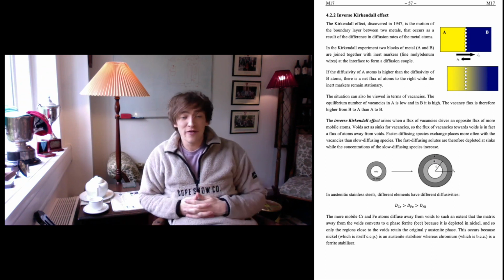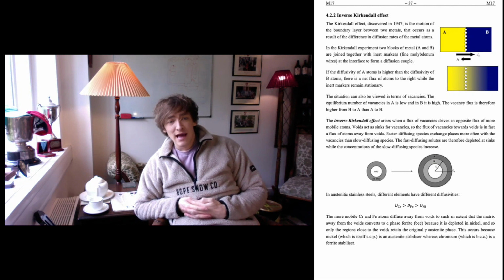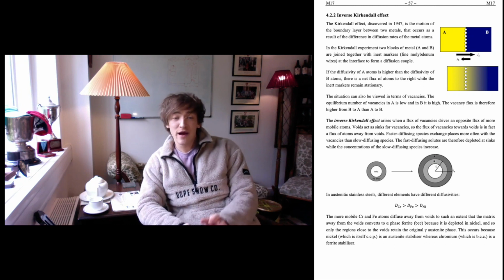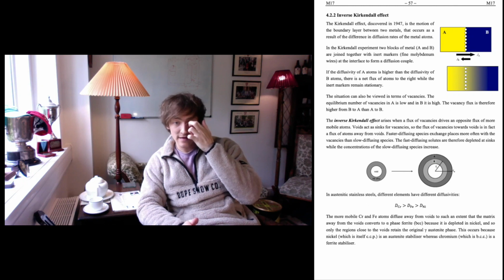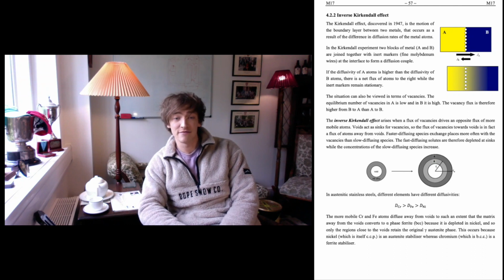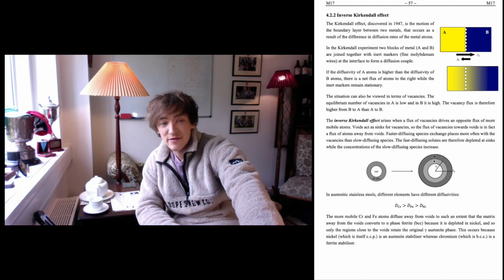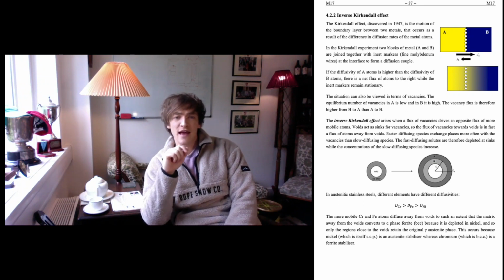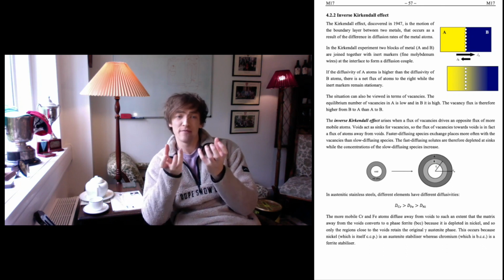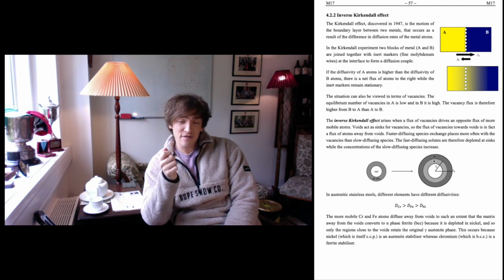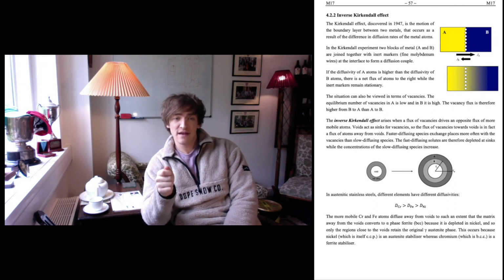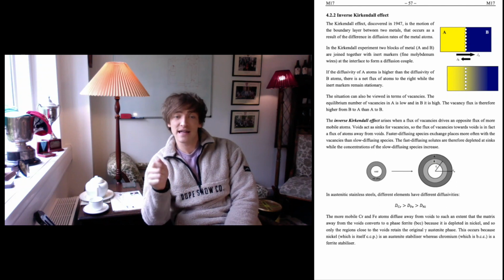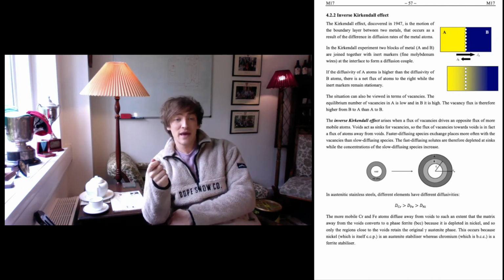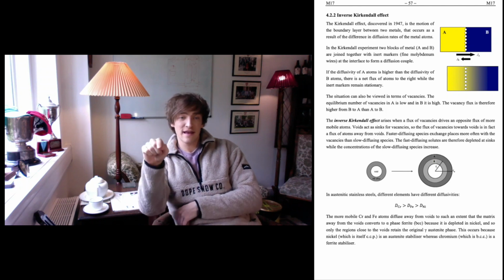Unfortunately, there's other phenomena that we need to be worried about. As always in nuclear, there's multiple problems. And one of those important phenomena we need to be aware of is the inverse Kirkendall effect, as this effect can cause compositional variation across our cladding, for example. Now this effect is represented in the graphs to the right here on page 57 as the motion of a boundary layer between two different metals, A and B. And it's due to the different diffusion rates of the two metal atoms. So let's take A. If the diffusivity of atom A is faster than that of atom B, then there is a net flux of atoms from A to B. So the boundary appears to move to the left, which is shown in the second image.